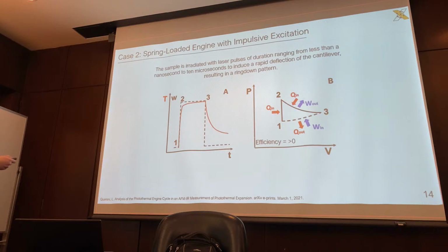So in this case, on the left-hand side, we're plotting the temperature of the system as a function of time. So if we take this dot to be our, from 1 to 2, the on signal for our laser, the duration of this laser pulse is the pulse width. And then from 2 to 3, laser turns off. And we can see the heat profile of our actual sample, where the sample doesn't heat up exactly how our laser does. We actually see a loss right here, where our sample doesn't reach peak temperature until about zone 3, where we turn off our laser.